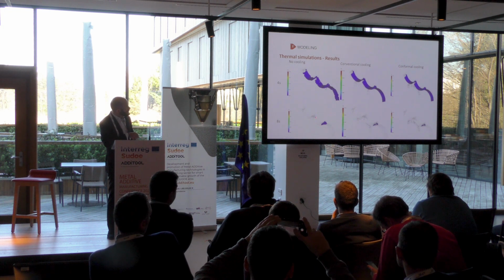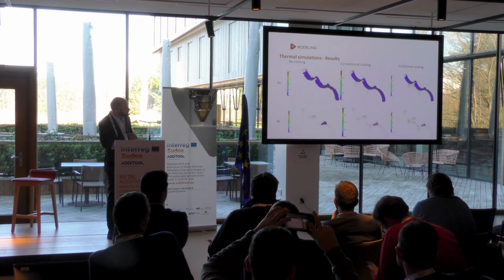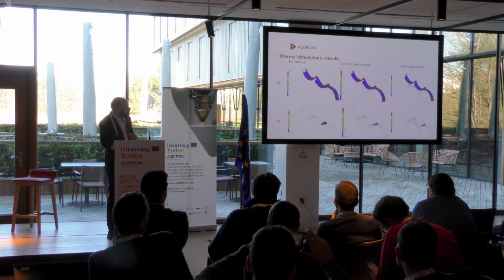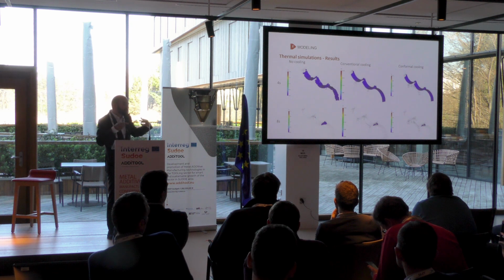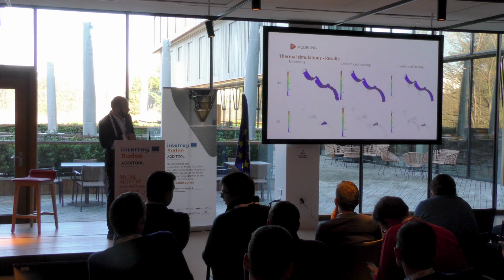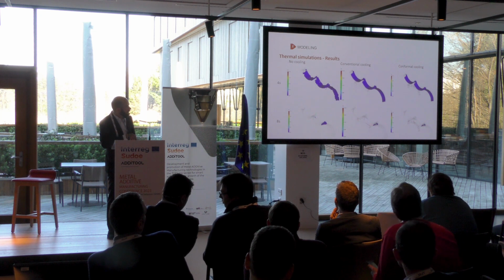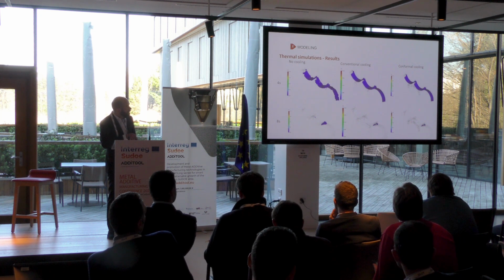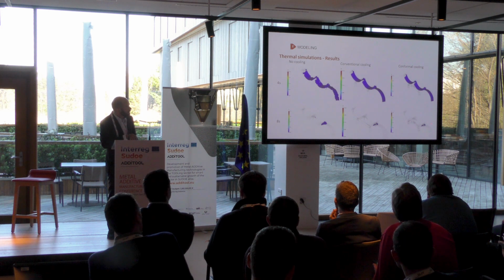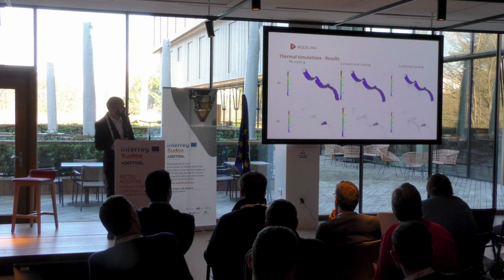After 8 seconds, we can see that without any cooling there are still blue areas with melted plastic. With conventional cooling, that is, using conventional drilled channels, we get a significant reduction of these still-melted zones. Conformal cooling is even better - a little bit better, but somewhat better.